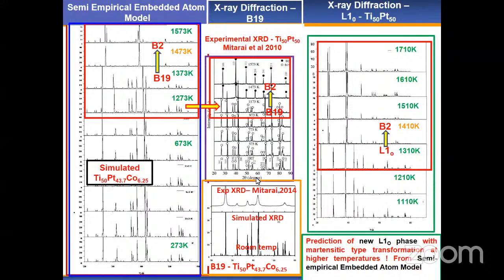Now, this is one complicated slide, but it also talks to the transformations that can be predicted by generating these X-ray diffractions. Importantly, to do this, you need quite a number of calculations. You perform quite a number of calculations so that you're able to plot as many XRD patterns as possible, so that you do not miss your transformation, because other systems will transform very quickly and you might miss that transformation temperature. So then you need a lot of resources to achieve this kind of analysis.